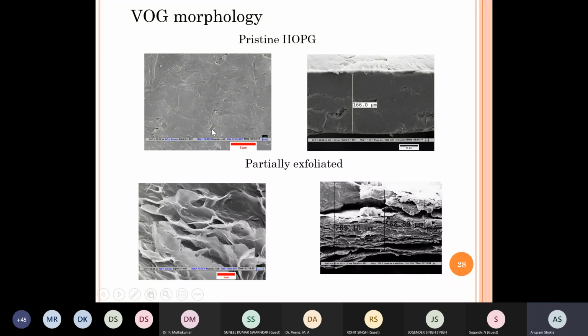Here is some of the characterization just in brief. So these are SEM micrographs of the graphite electrode. So this is pristine HOPG, highly oriented pyrolytic graphite, synthetic graphite. This is the top view. And on the right hand side is a cross view where you can see the layers are so tightly stacked that one cannot make out the layers. Okay.